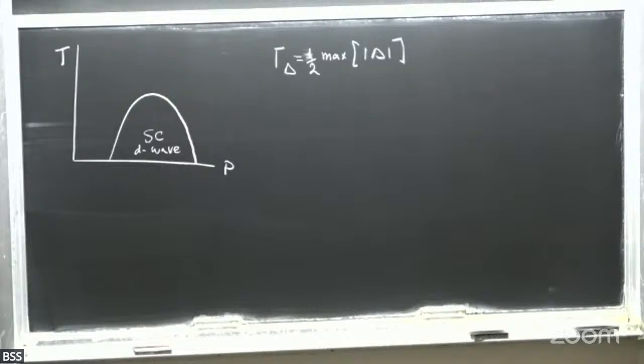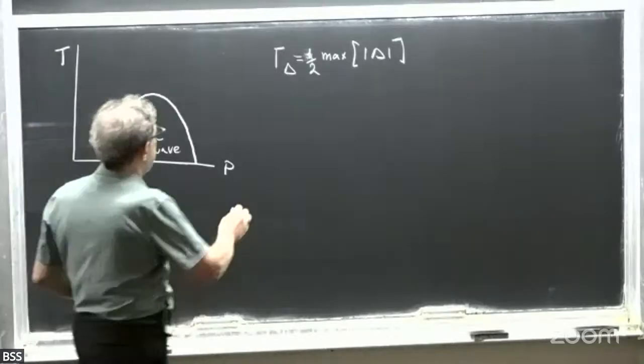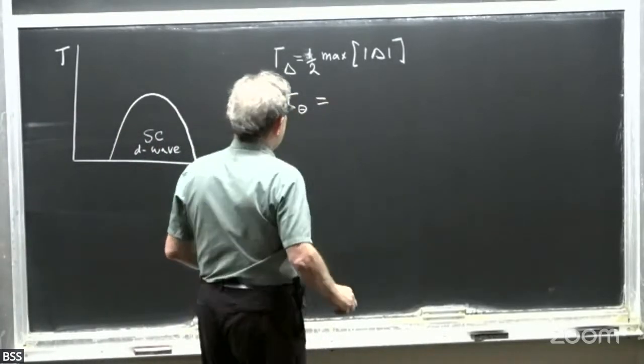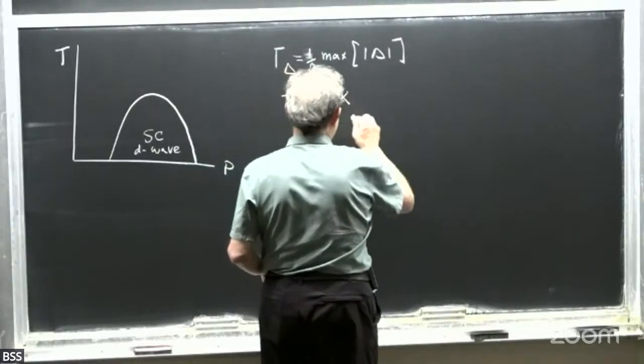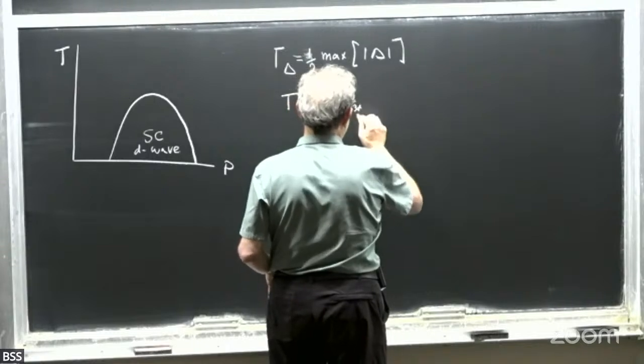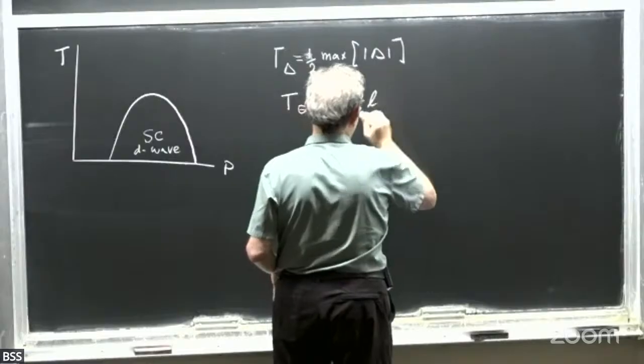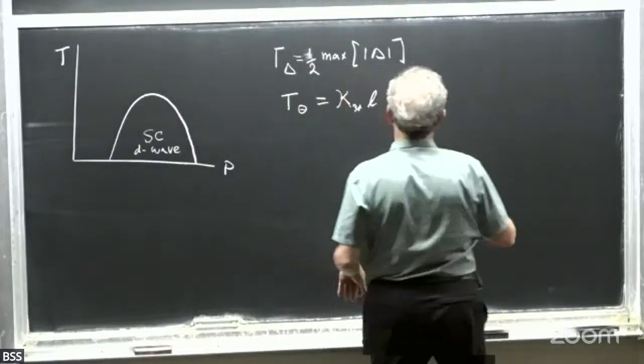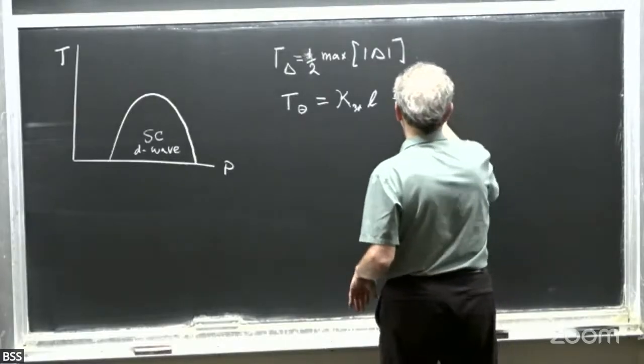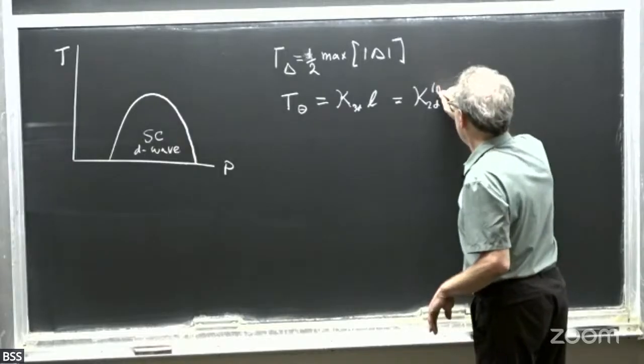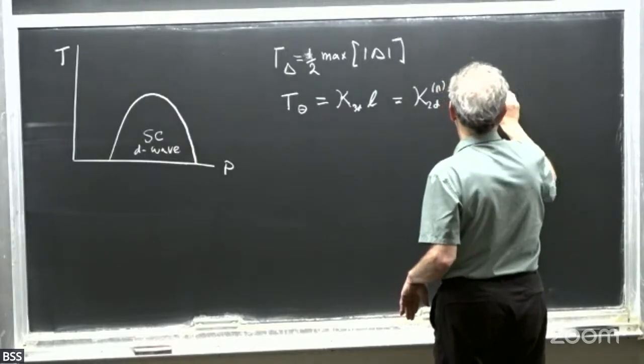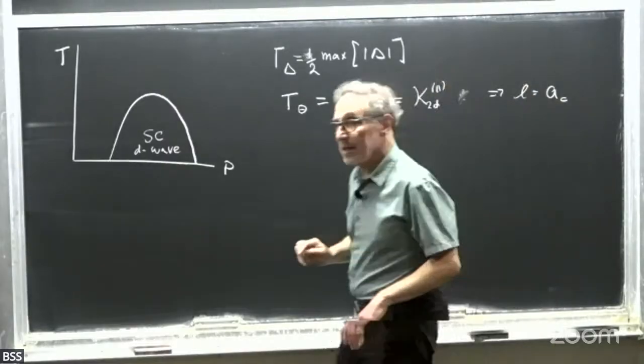The gap is telling us something about how strongly pairs of electrons are bound to form bosons. And so these thermal fluctuations tell us about at what temperature scale the bosons fall apart. And then there is another temperature scale, which can be written like this. It's kappa 3D times some length, or in a quasi two-dimensional system, this is kappa 2D, the stiffness in plane, which corresponds to L equals the lattice constant in the c direction.